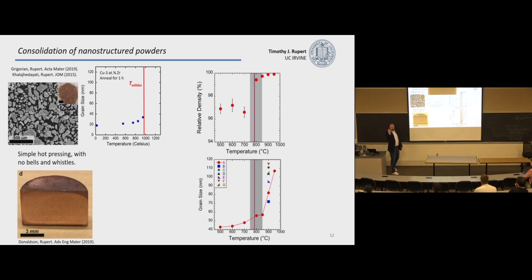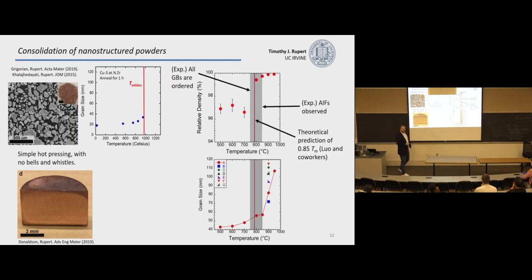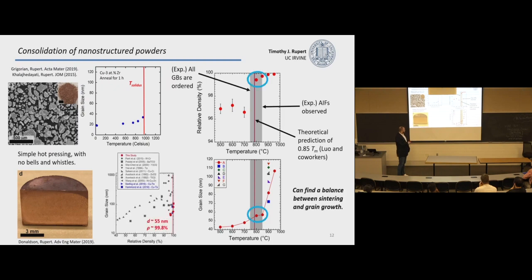We make these in my lab, they're chunks this big, and we can study the processing. I'm less interested in talking too much about that today. But the basic idea is this marked area right here is where we start to get those amorphous complexions. The gray area is from experiments, the purple one is from theory, but they're showing us that that's where we start to get amorphous grain boundaries. And that's where we get a big jump in the density of these pressed samples, but our grain size still stays relatively small, and we can make 100% density materials with a grain size of about 50 nanometers.